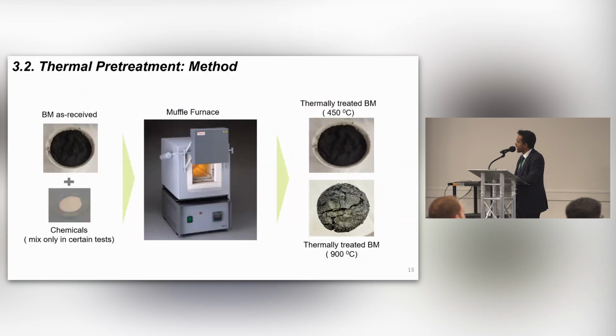We also tried thermal pre-treatment methods. For some tests, we mixed some chemicals before introducing the black mass into thermal treatment. We varied the temperature and also the retention time. You can see at the different temperatures, we got black mass with different appearance. Basically, at a very high temperature, we observe the black mass turned into a hard type because some metallic oxide converted into metal form.